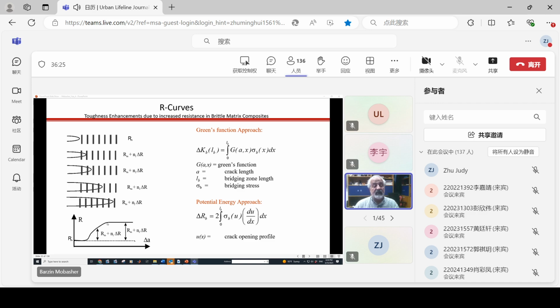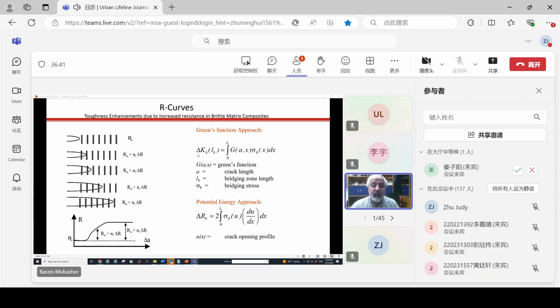So the material now has a toughness that may be 3 times as high as here. And that can be calculated. We've shown it in papers, several papers. That's a Green's functions approach that we can actually calculate by loading-unloading tests. And we can calculate how much toughening we get from a strain energy release rate calculation or the R curve calculation. Both of these can be shown to be very similar.